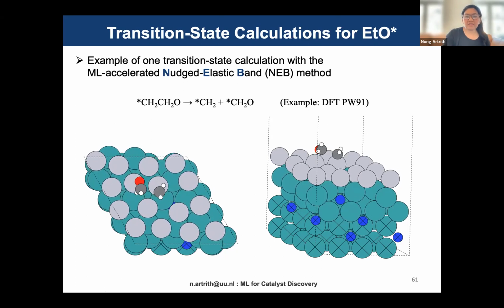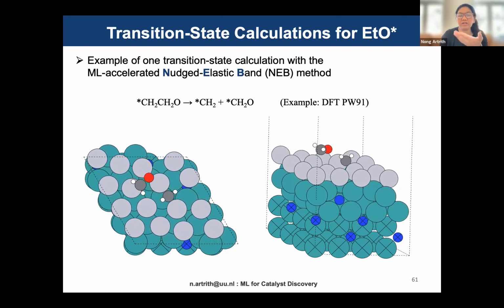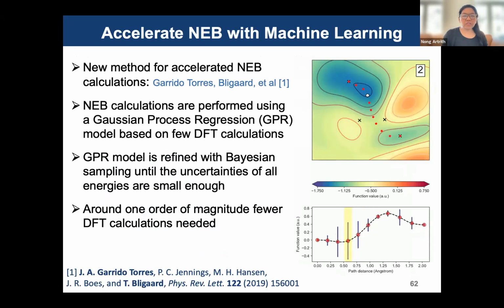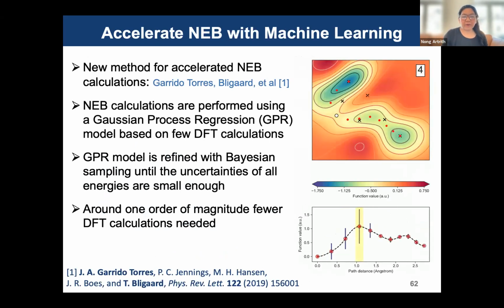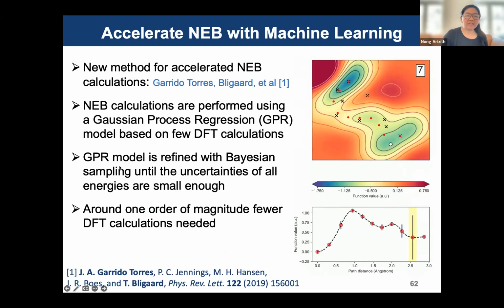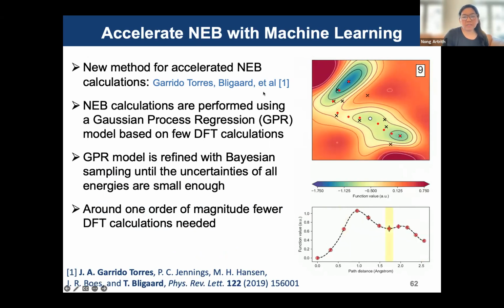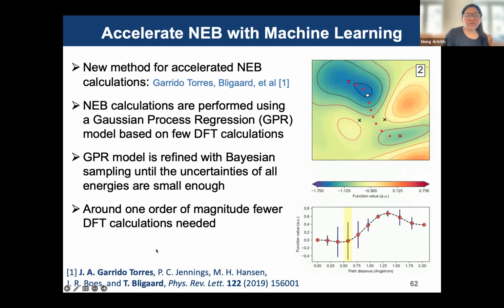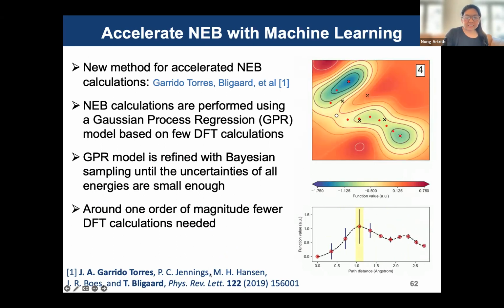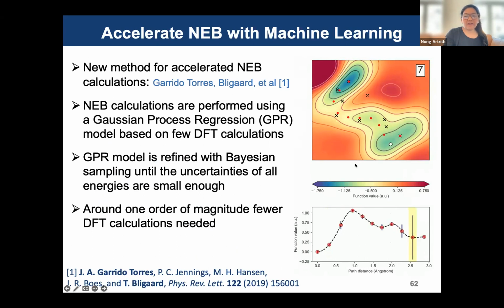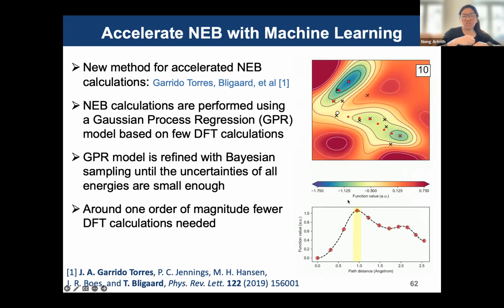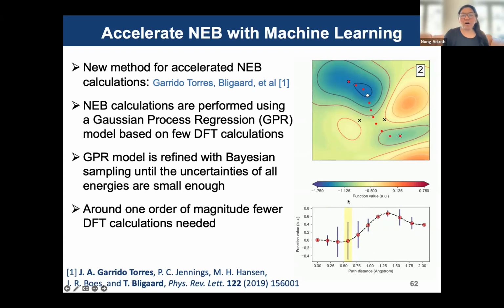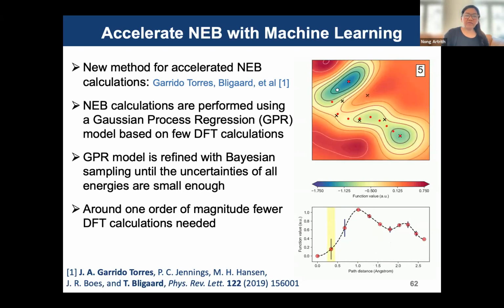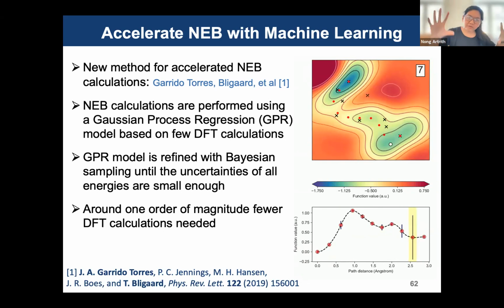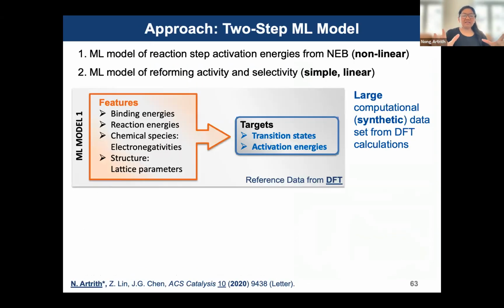So as the first step, we use machine learning to help accelerate finding the transition states of the calculations. We use the machine-learning nudged elastic band, or the NEB method, which makes use of Gaussian process regression, the GPR models developed by Jose and also Thomas Bligaard, at that time at Stanford but now at DTU. So if you are interested in this method, I also put the references here. Basically, we have to automatically search the activation energy for all paths, like the ones I labeled before from the reaction networks. And then we collect the features and also the target that we want to have.